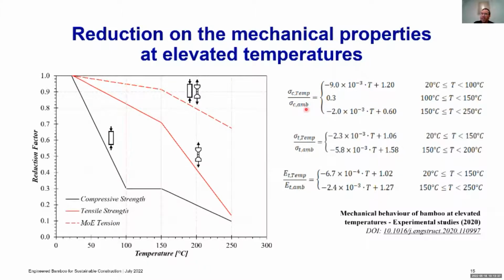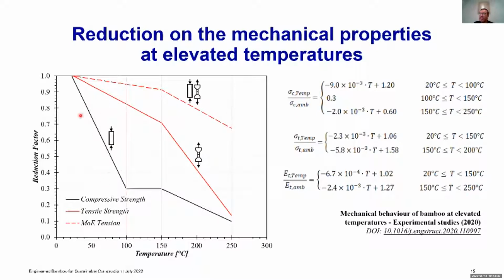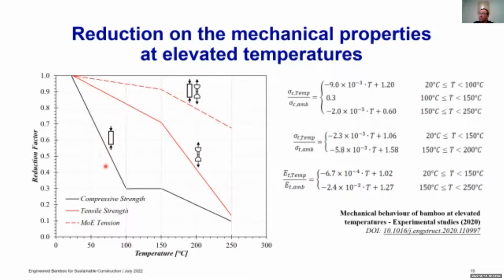So yeah, you can clearly see here that below 100 degrees, the loss in the compressive strength is huge, which is quite similar to what you have in timber, maybe a little bit higher reduction, but there is less effect on the tensile strength.